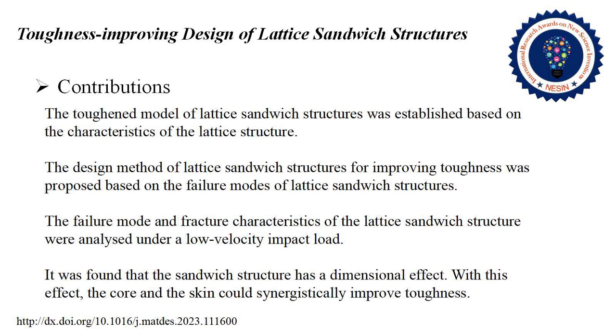First, the toughened model of lattice sandwich structures was established based on the characteristics of the lattice structure. Second, the design method of lattice sandwich structures for improving toughness was proposed based on the failure modes of lattice sandwich structures. Third, the failure mode and fracture characteristics of the lattice sandwich structure were analyzed under a low-velocity impact load. Last, it was found that the sandwich structure had a dimensional effect. With this effect, the core and the skin could synergistically improve toughness.